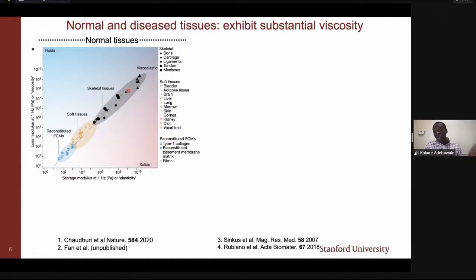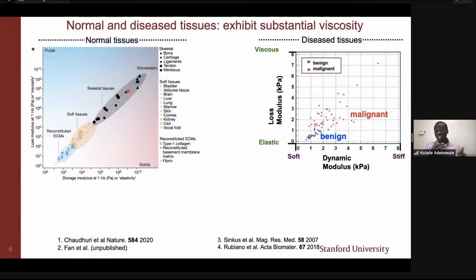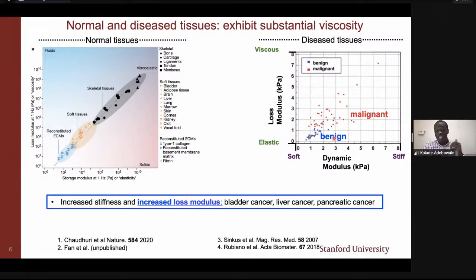But not only is this property of viscoelasticity important in the context of normal tissues, it's also being implicated in diseased tissues as well. On the graph on the right, you're looking at the loss modulus on the y-axis as a function of the dynamic modulus or stiffness on the x-axis of human tumor samples. What this data suggests is that malignant breast tumors are not only stiffer, but they also have a higher loss modulus, which means they have more viscous properties compared to benign breast tissue. And this increase in both stiffness and loss modulus has been found for not only human breast cancer, but also bladder cancer, liver cancer, and pancreatic cancer.